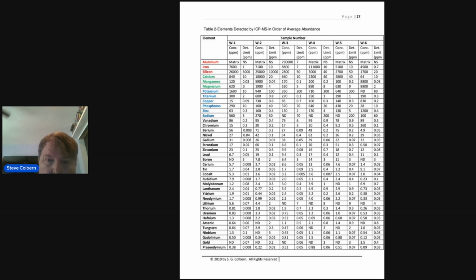And W5 had a lot less, 5,100 ppm, 4,500 ppm in W6. Silicon was a big contributor, 26,000 ppm in W1 and less in the other samples. I kind of hypothesized that these samples may have been acting as electrical conductors, and if so, perhaps they used iron and silicon, maybe for other reasons too, but because iron and silicon do not interfere with the conductivity of aluminum as much as other alloy ingredients would.